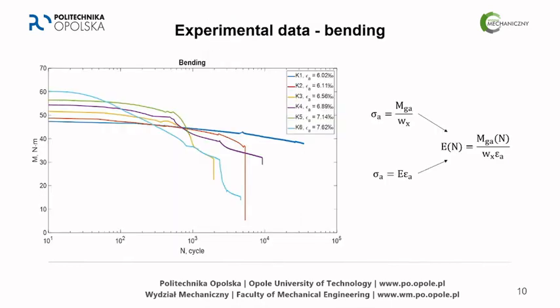Moving on to the experimental data, let's take a look at the graph presented on the left of this page. This is the bending moment as a function of number of cycles. What's interesting in this graph is that when the strain amplitude is low, then it doesn't change so much when the number of cycles increase. However, when the strain amplitude was the biggest at the beginning, it decreased so much that it was actually the lowest at the end. And on the right side of this page, we can see that based on the basic formulas from strength of materials, we can derive the formula for the Young modulus, which was used in the next stage of the research.